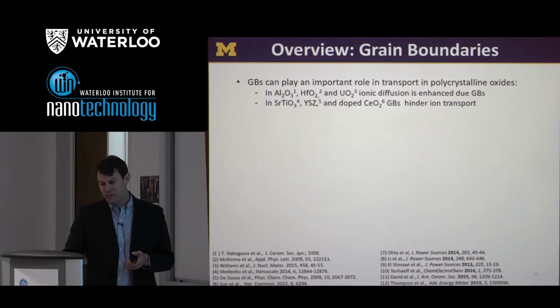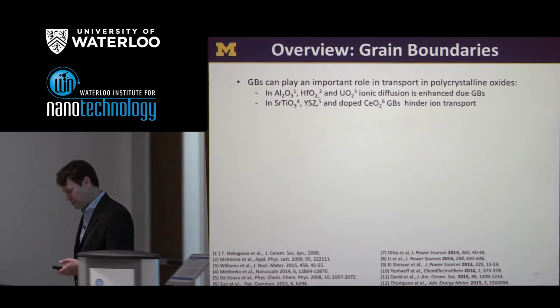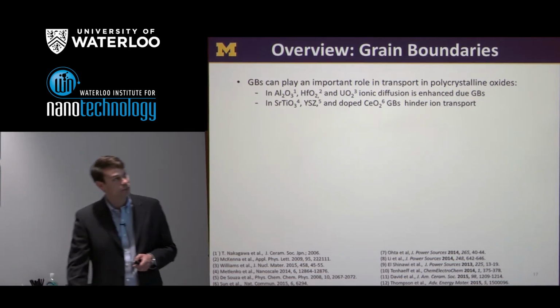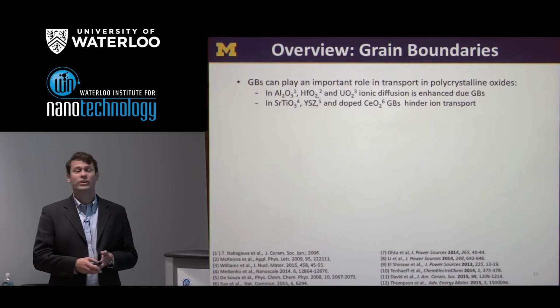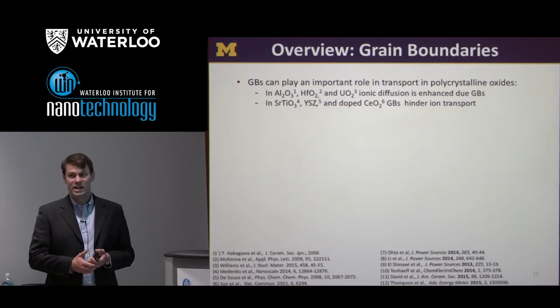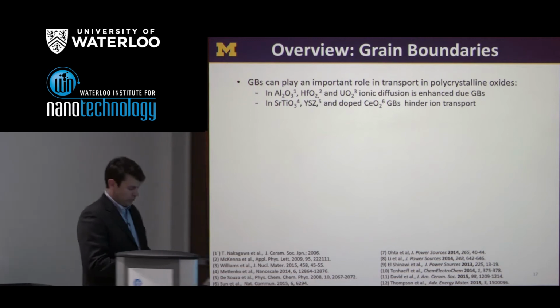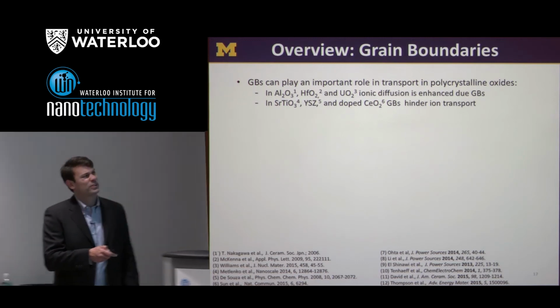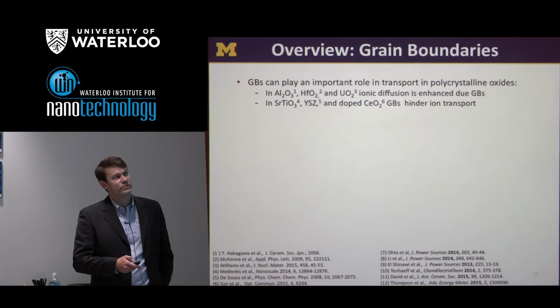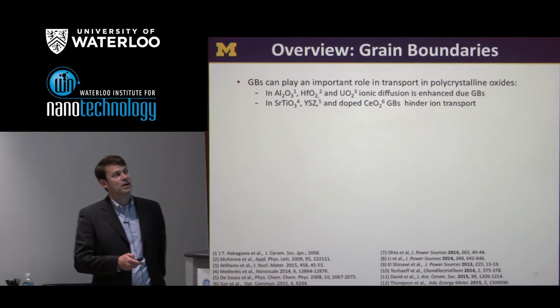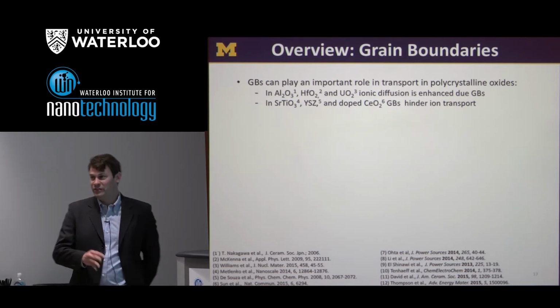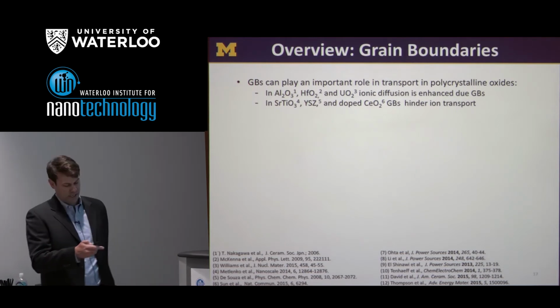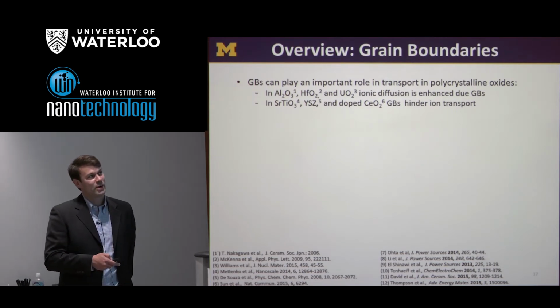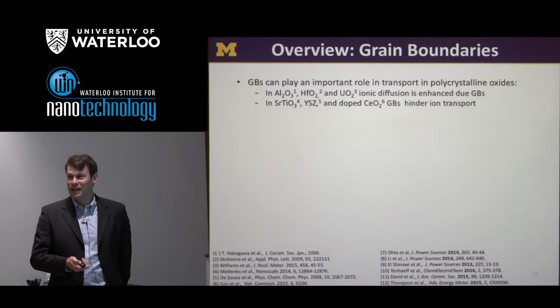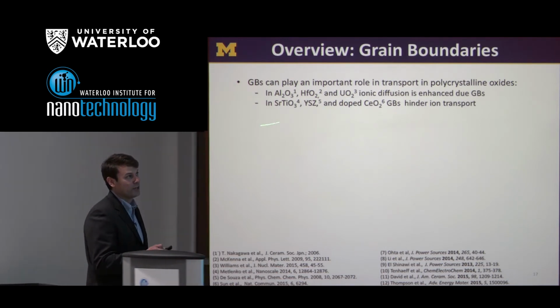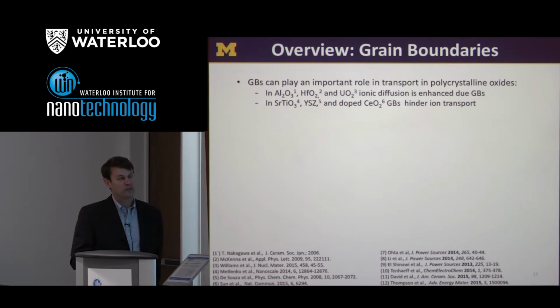So that brings me to the second part of the talk, where, as a segue into looking at what effect grain boundaries have on the performance of LLZO, we've started out by looking at transport along those grain boundaries. Before we get into this, I think it's important to have some history about how grain boundaries affect ionic transport in other oxides or other solids. Basically, you can have any possibility here. For things like aluminum oxide, hafnium oxide, uranium oxide, ionic diffusion is enhanced by grain boundaries, but in other compounds, grain boundaries slow ion transport.